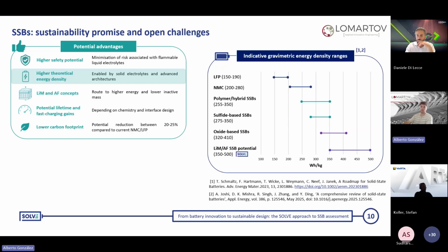This is directly linked to the third advantage, which are the lithium metal and anode-free concepts. And this is because by reducing or removing the conventional graphite anode, these architectures can reduce inactive mass and open the door to more compact cells with higher energy densities. There may also be gains in terms of lifetime and fast charging, but this is also highly dependent on interface stability and lithium plating control.